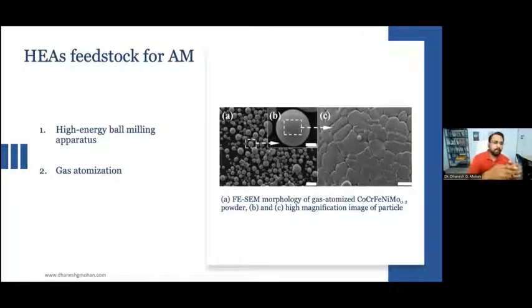First of all, we used a high energy ball mill apparatus. It's a mechanical process. By using this process, we ball mill the entire material in a container for 48 hours, up to 3 days. Afterwards we found that this material was not what we accepted. The output from the ball mill could not be used directly in additive manufacturing. So again, we used the gas atomization method. Gas atomization is nothing but using argon gas. For our experiments, we used argon gas. We heated the argon gas and sprayed the molten metal onto a substrate and received this material. You can see the image over here, the microstructure of this.